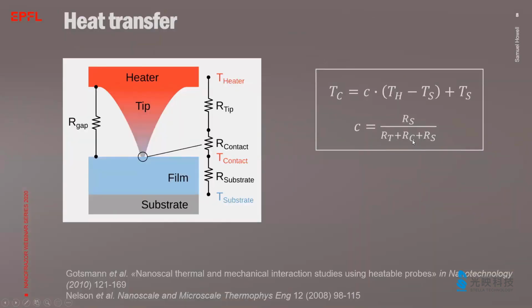First, the maximum temperature is limited by the heating power of the heater in the cantilever. With modern resistive silicon heaters, temperatures of 1200 degrees Celsius can be easily achieved. But more interesting is the temperature at the tip-sample contact, which is typically much lower than the heater temperature. The first important parameter is the thermal conductivity of the tip and the film and the substrate, which determine the temperature at the contact.